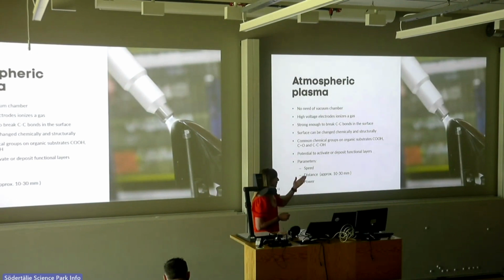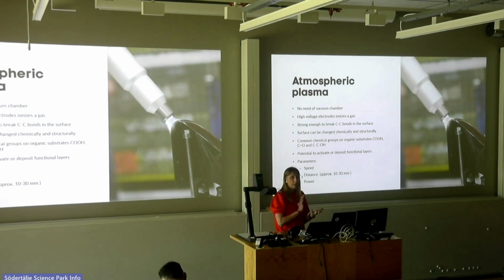As with laser, here you program your process, so you need to keep track of the distance, which is quite critical. From 10 millimeters up to 30 are typical numbers for the ones we use, and if you go too far away, then you don't have the effect on the surface. So the distance from the substrate to the nozzle, and then the speed, of course. And there are various types of plasma nozzles and shapes, so you can make a tailor-made solution for your products or processes.